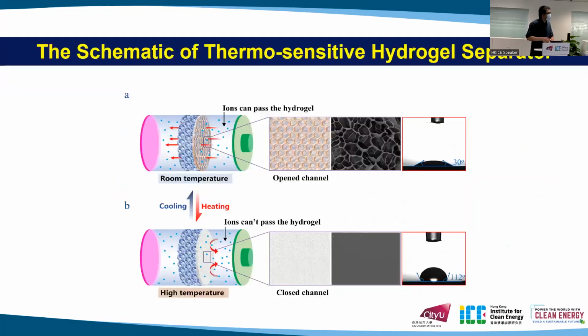So we want to get a porous hydrogel that could let the ions migrate and transport through it at room temperature, but with carefully controlled thickness, which also could provide decent electrical performance. And after heating, the channels for ion migration will be blocked, and most important, it should be reversible. So how do we achieve this?